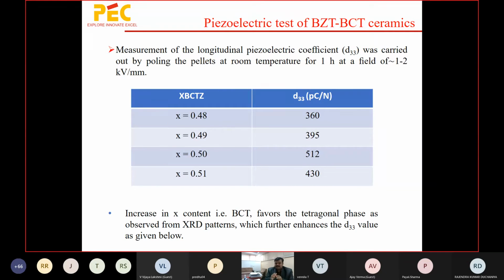And for this particular material, people have reported nearly 600. But when we started the work in our lab, we tried a lot to go beyond 400, but somehow we were not able to. Then we changed the synthesis method, getting help from the SSPL, the Solid State Physics Lab of DRDO at New Delhi. They suggested some modified methods, and we used them, and we got this high value.